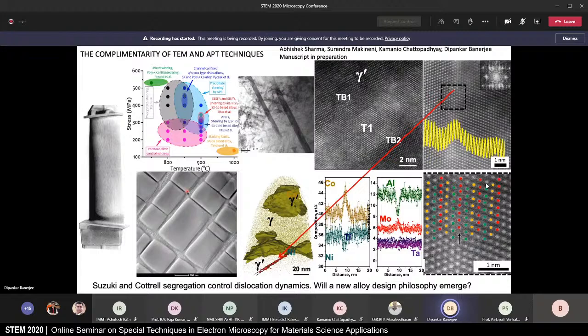And I want to talk to you about some examples of the shearing process to illustrate the power of combining TEM with atom probe tomography. So here is an example of now atomic resolution, high angle annular dark field microscopy. So this high resolution work with HAADF is high resolution of these twins that result in this structure when Ni3Al is sheared at this low temperature, high stress regime. And what the HAADF immediately tells you is that there is a composition segregation in these twins. So energy dispersive, and you can look at the intensity difference here between the twin and the matrix. A higher resolution picture of these interfaces also tells you that there is additional segregation at the twin matrix boundary interfaces.